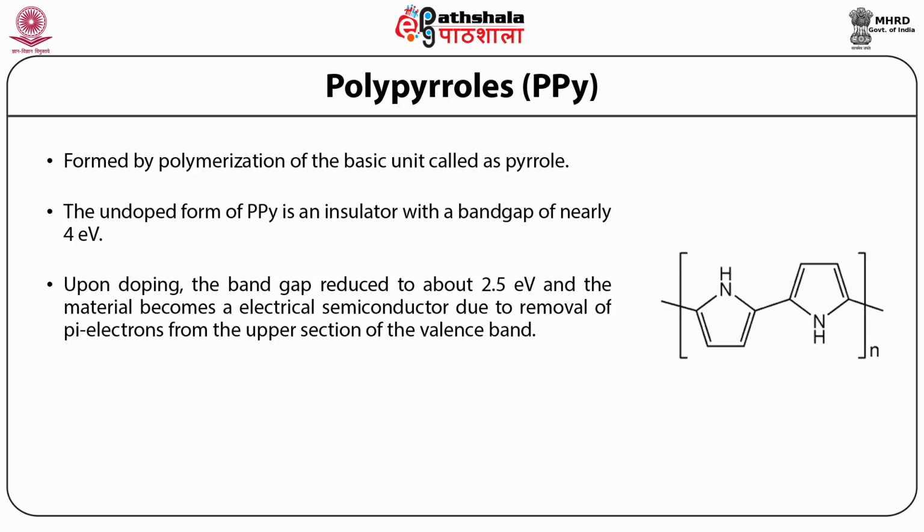Thin films of undoped polypyrrole have a yellow color which becomes darker upon exposure to oxidizing, such as doping, conditions, leading to blue or black films depending on the degree of polymerization as well as film thickness. Doping also tends to render the polypyrrole brittle. Also, both undoped as well as doped films have no solubility in the common solvents.